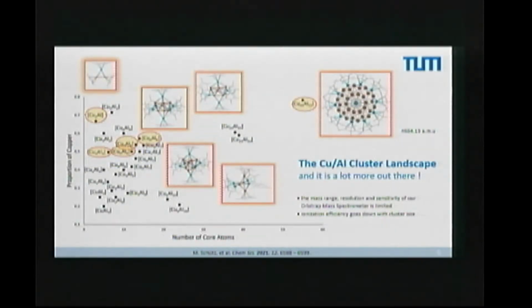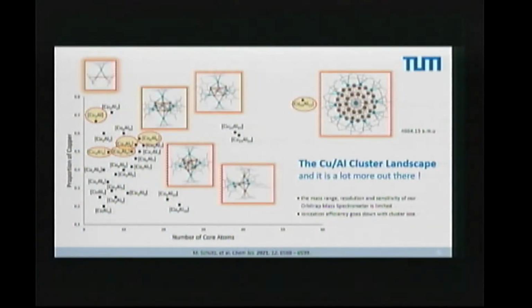So this is part of the copper aluminum cluster landscape, which we can obtain by just combining the copper precursor and the aluminum precursor. On the x-axis here, we have the number of core atoms. So we count together the copper and the aluminum. So 10, 20, 30, etc., 50 atoms. And here is the proportion of the copper. So for example, our small candidate here, 2 coppers, 1 aluminum. The candidate over there would be a copper 8, aluminum 6, and all these circles here and the squares mean these are candidates, these are clusters, these are compounds we can make and isolate, characterize rigorously by X-ray single crystal structure analysis, NMR spectroscopy, IR spectroscopy, by all kinds of spectroscopies precisely.